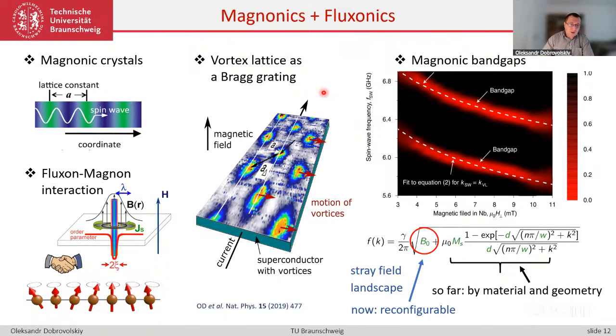dictated by the transport currents. So if we apply a transport current to a superconducting film at currents which exceed the depinning current, the vortex ensemble will be set in motion. So this magnetization or stray field landscape will be displaced from left to right, so in the direction perpendicular to the transport current.